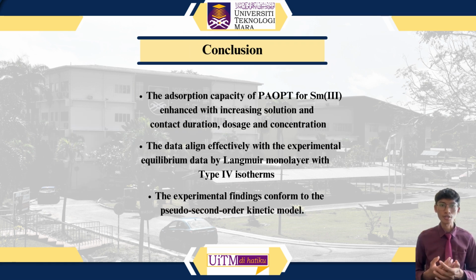In conclusion, the adsorption capacity of PAOPT for samarium is enhanced with increasing solution pH, contact duration, dosage, and concentration. The data align effectively with the experimental equilibrium data by the Langmuir monolayer with type 4 isotherm. The experimental findings also conform to the pseudo second-order kinetic model.